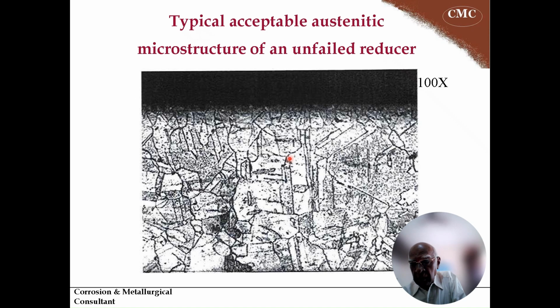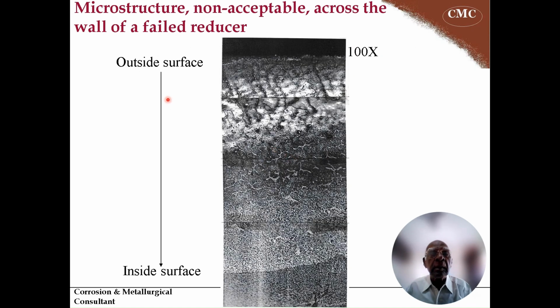On the other hand, the failed reducers show a differential microstructure. As you see here, the outside is coarse grained, and then inside the grain size gradually reduces, with finer grain size on the side seeing the gases on the inside. This is the gas flowing here, and this is the outside, where hot gases used for heating the tubes are. This differential microstructure is not acceptable across the wall of a failed reducer.